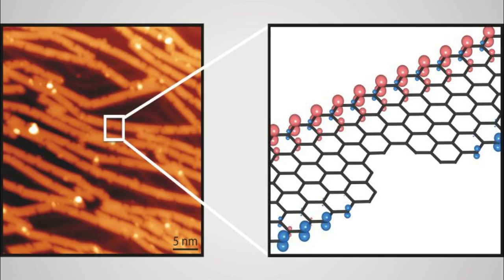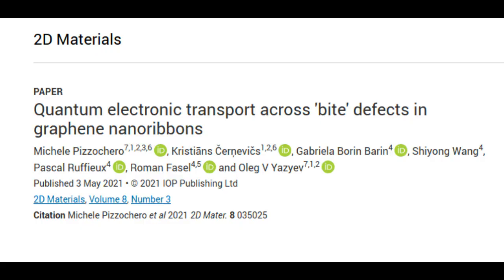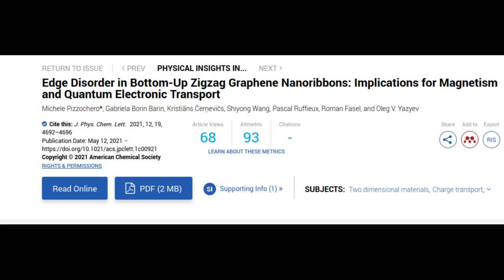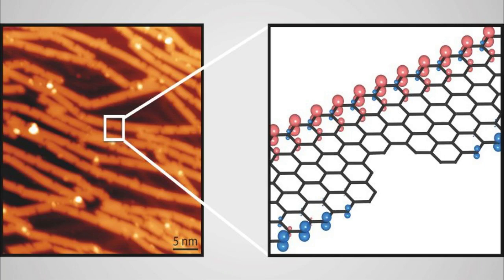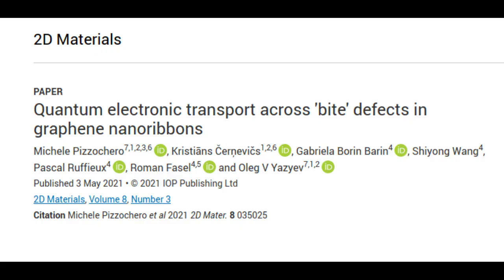Collaboration between researchers at EPFL and EMPA has produced two papers that look at this issue in armchair-edged and zigzag-edged graphene nanoribbons. The researchers say that in these two works, they focused on characterizing bite defects in graphene nanoribbons and their implications on GNR properties. The researchers observed that even though the presence of these defects can disturb GNR's electronic transport, they could also yield spin polarized currents. These are important findings in the context of the potential applications of GNRs in nanoelectronics and quantum technology.